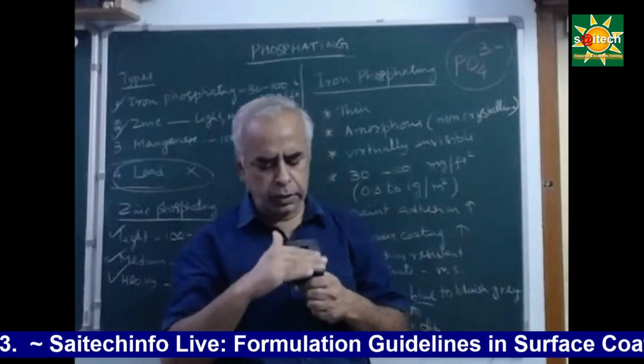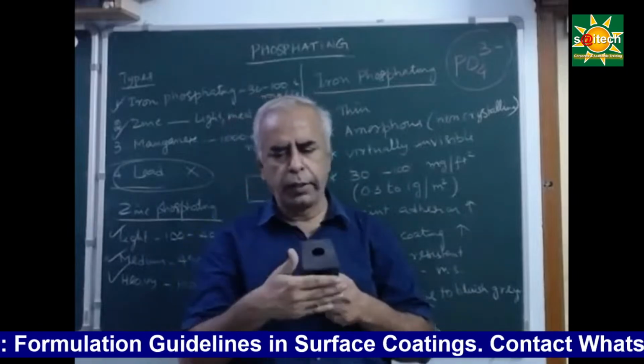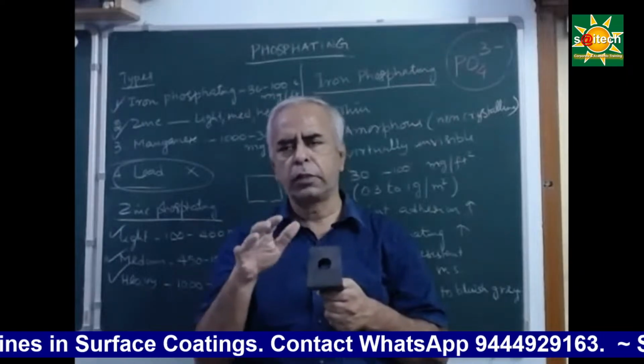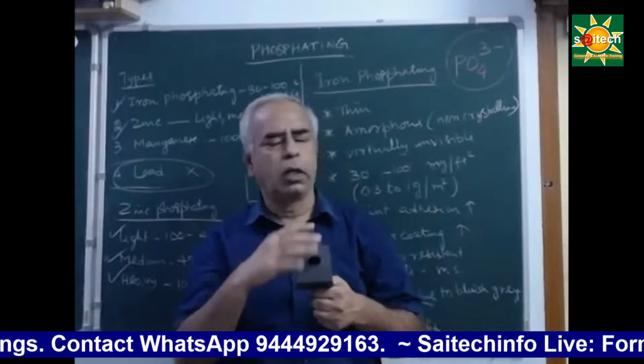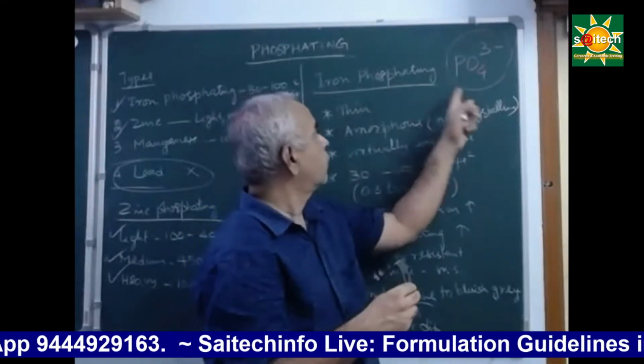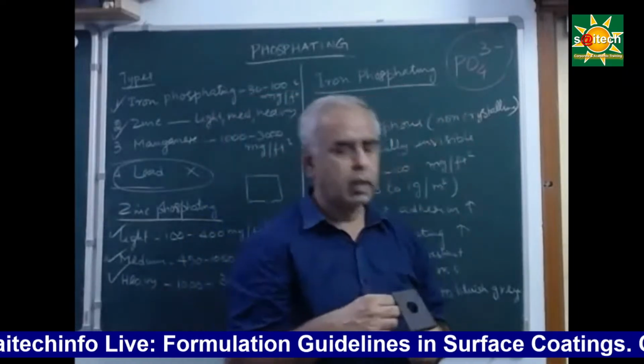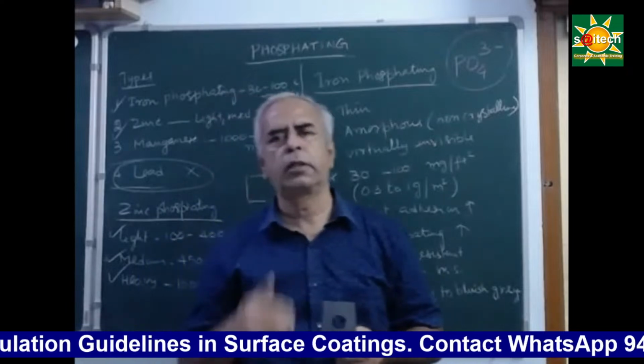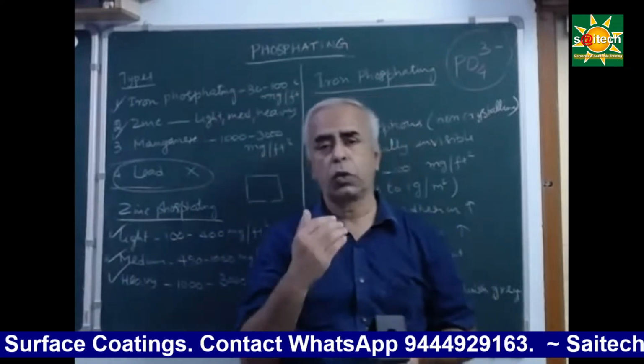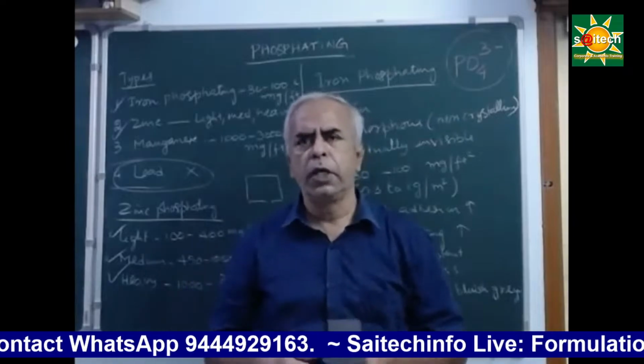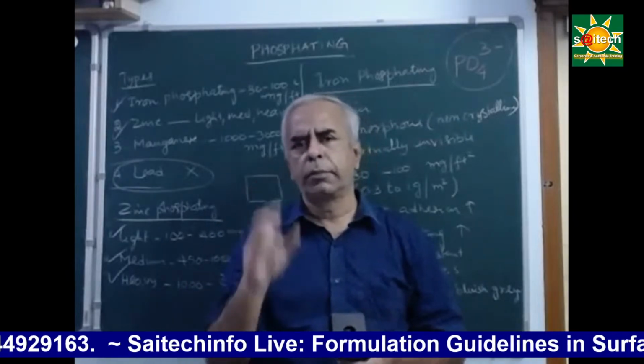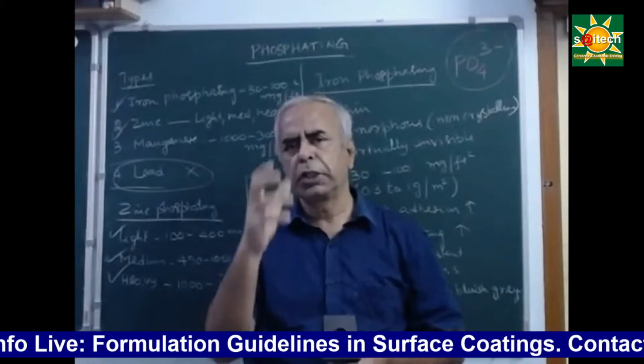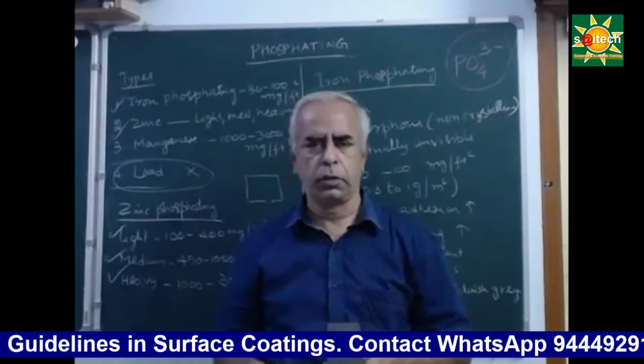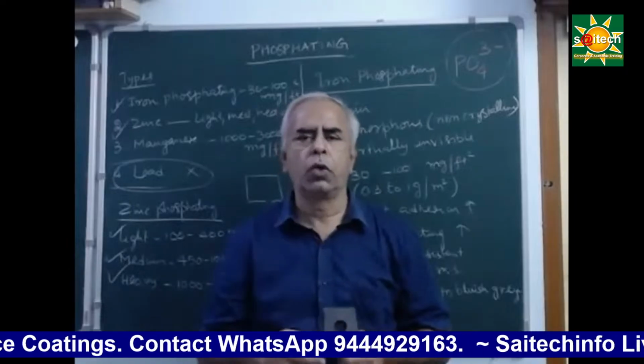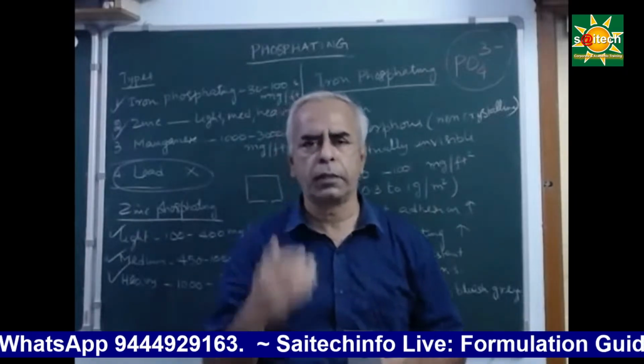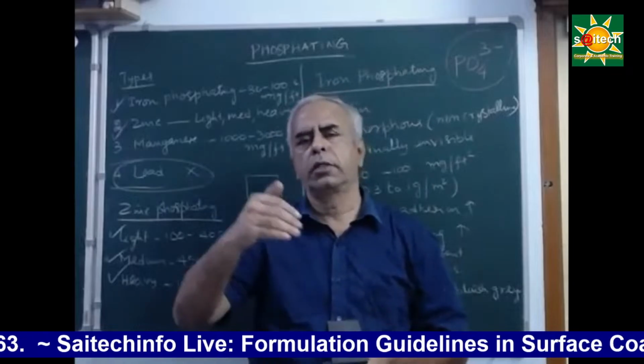If it is mildly coated, then furniture enamels, furniture paints can be given on that lightweight iron phosphate coating. So that is recommended. But if you insist on better salt spray resistance, that is corrosion resistance, usually salt spray is the testing parameter useful for measuring the extent of corrosion resistance. We give it in terms of salt spray resistant hours, according to ASTM B117.